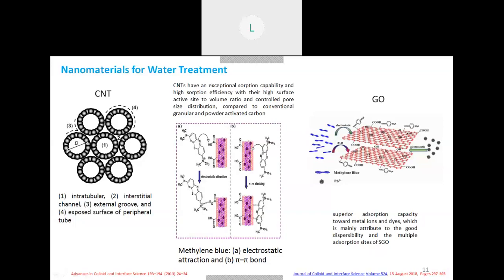So majorly the active site is the outer surface. This is an example of removing methylene blue by the various mechanisms given by the CNTs. Because of the various functional groups present on the surface of CNTs, the dye can be removed by electrostatic interaction or pi stacking.